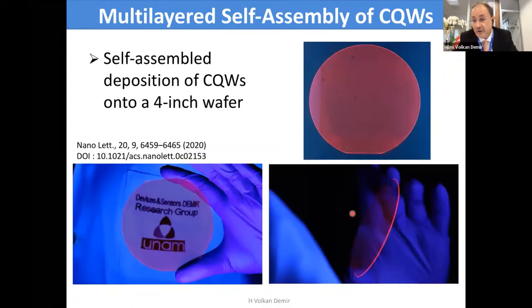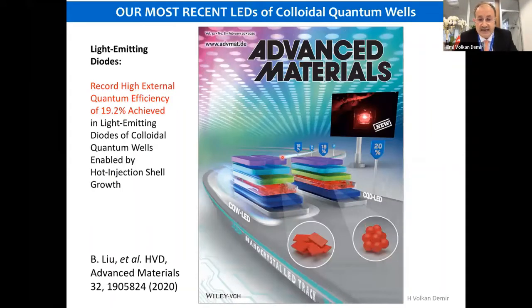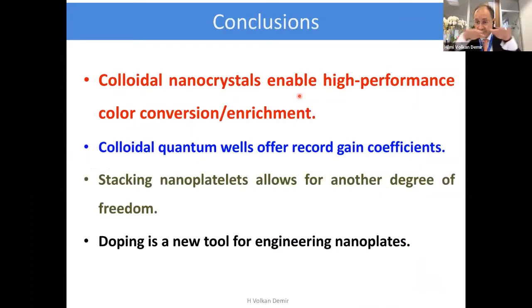This is a four-inch wafer, which corresponds to larger than 80 square centimeters. And this is almost my final slide here. You can really make active devices out of these colloidal quantum wells. This is in 2020, showing that we can actually achieve record high external quantum efficiency close to 20%. This is pretty much the theoretical limit. And this puts us on par with colloidal quantum dot materials, perovskites, and so on. So we think, as also highlighted on the cover of Advanced Materials, this is really a new pathway for the entire community to make active devices out of these atomically flat materials.